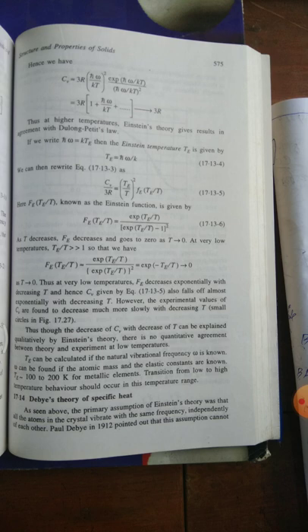This is equal to exp(minus θE/T), which tends to 0 as T tends to 0. Thus at very low temperature FE decreases exponentially with decrease of T, and hence Cv, given by the equation Cv by 3R equal to (θE/T) squared FE(θE/T), also falls off almost exponentially with decreasing T. However, the experimental values of Cv are found to decrease much more slowly with decreasing T, shown by small circles.